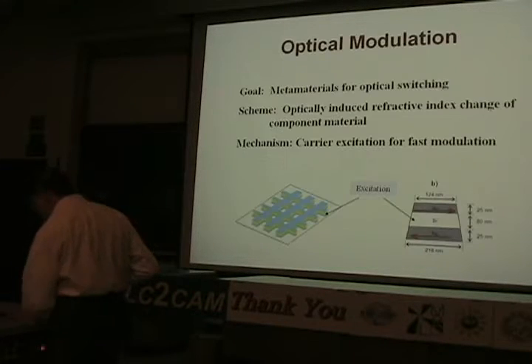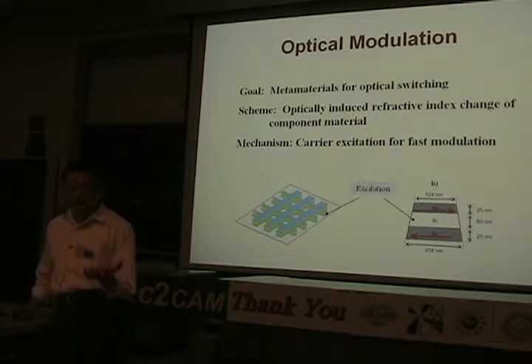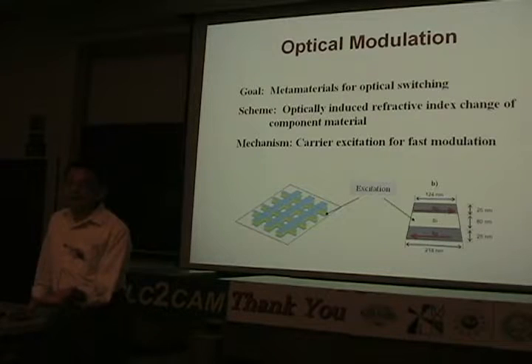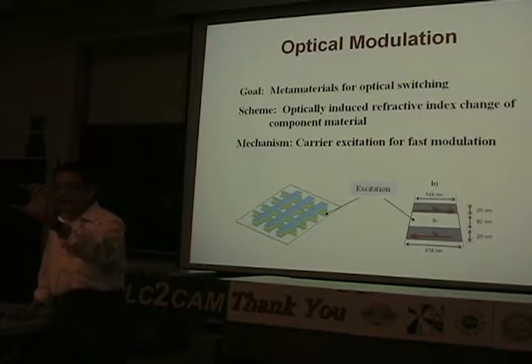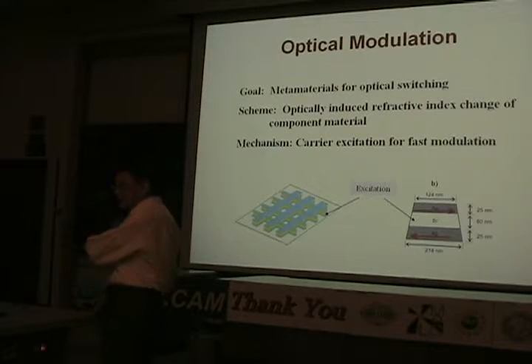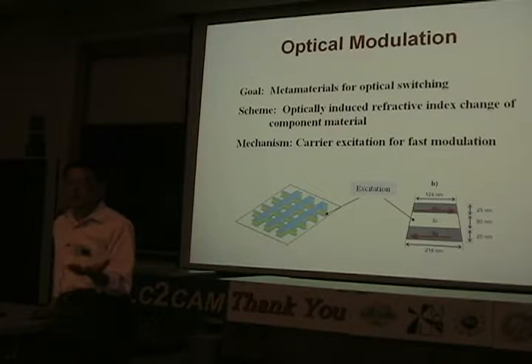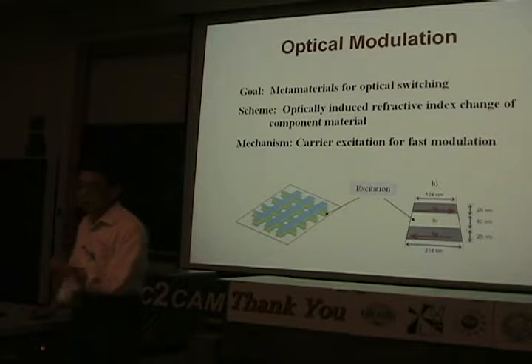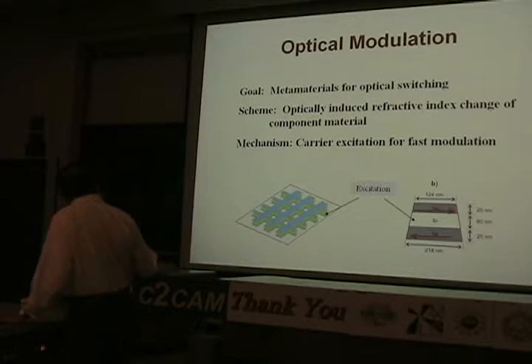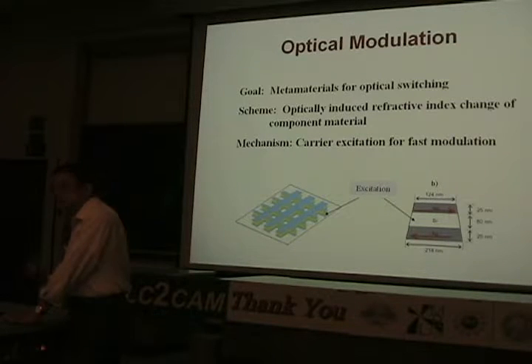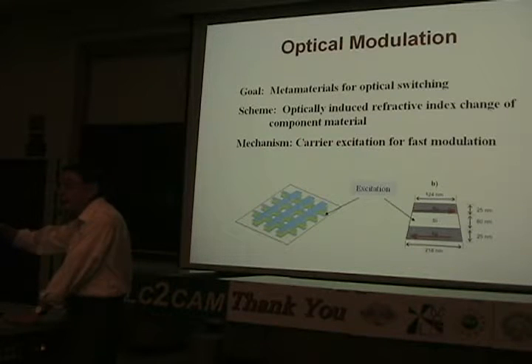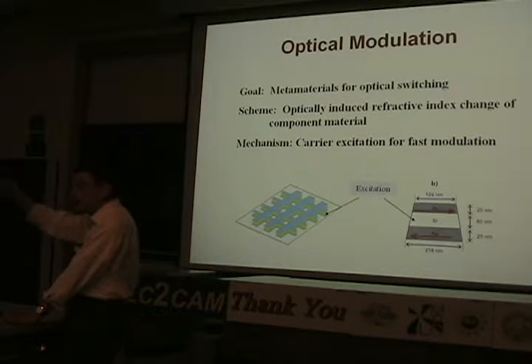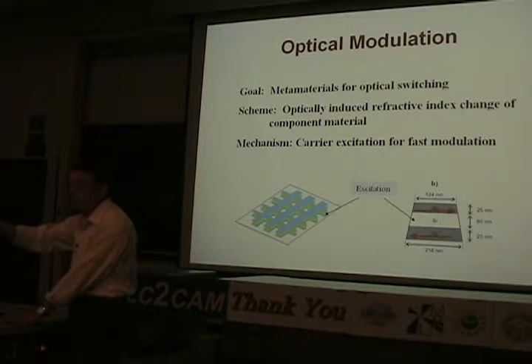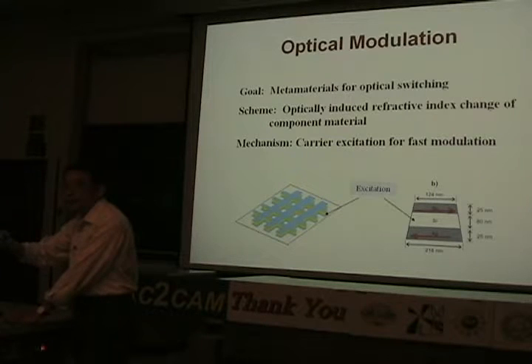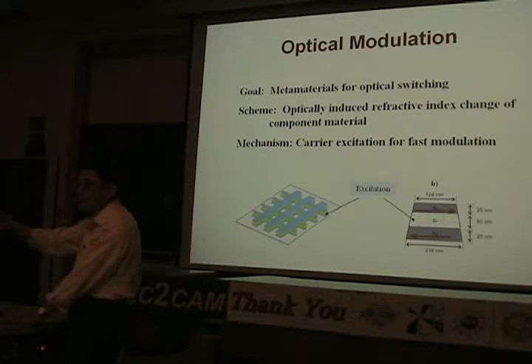So with this, we are pretty sure that we do have a negative refractive index material. The only problem is how to make this material thicker. This is almost just two-dimensional. What we really want is a three-dimensional structure so that you can see those effects much more easily. So the next thing is to see whether we can indeed get optical modulation. And now with silicon in between, we can easily excite the carriers in silicon. And with the carrier excitation, the refractive index of silicon is going to change. And if the change is strong enough, we should be able to see the change in transmission.